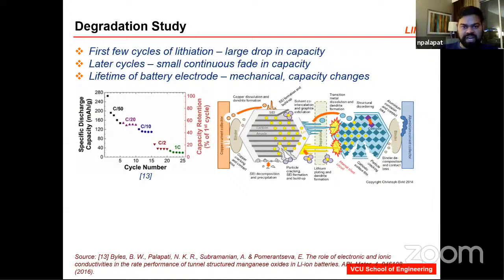For example, you have binders that can lose, that can crack. You have a solid electrolyte interface that forms at the anode. Then you have a separator material that, if not stopped, can cause dendrite formation. Then you have your cathode material that can break. This is what happens in your sulfur and silicon batteries. So I like this picture. I keep using this. It gives you, in general, all the different issues that actually go on in a battery.